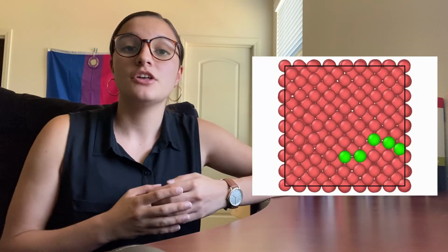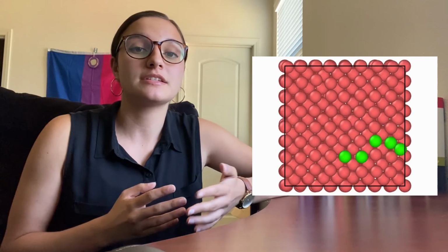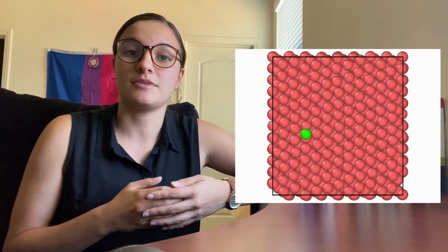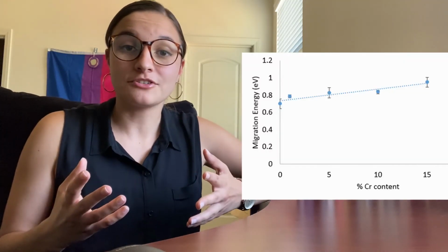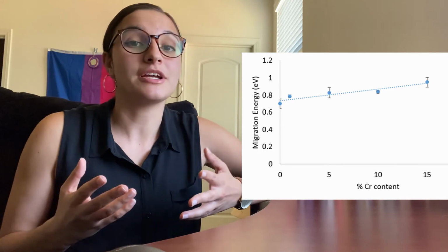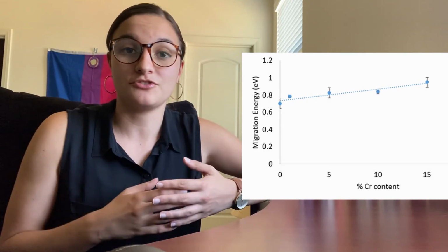In summary, we were able to study the two surfaces, 100 and 110, and collect data on the mean square displacement, the diffusivity, and the migration energy. We did this for multiple concentrations of chromium as well as different layers of chromium. We discovered different diffusion mechanisms between the two surfaces, the 100 having an exchange mechanism and the 110 not having an exchange mechanism. In the 100 surface, we noticed an increasing trend in migration energy with increasing chromium concentration.